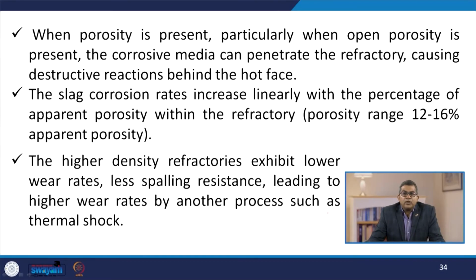Now, when porosity is present, particularly when open porosity is there, the corrosive media can penetrate the refractory, causing the destructive reaction behind the hot face. The slag corrosion rates increase linearly with the percentage of apparent porosity within the refractory, in a porosity range from 12 to 16% apparent porosity. The higher density refractories exhibit lower wear rates but less spalling resistance, leading to higher wear rates by another process such as thermal shock.